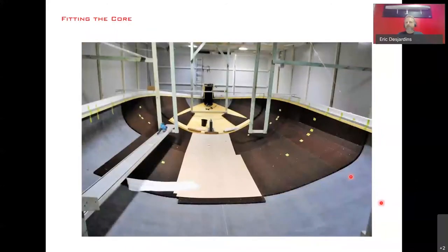These slides show the black is actually the outside skin of the hull that's been laminated and cured independently. And now it's time to fit the core. So you have two types of core on this picture. You have a foam core here, which is in a slamming area, which is highly loaded in the boat.